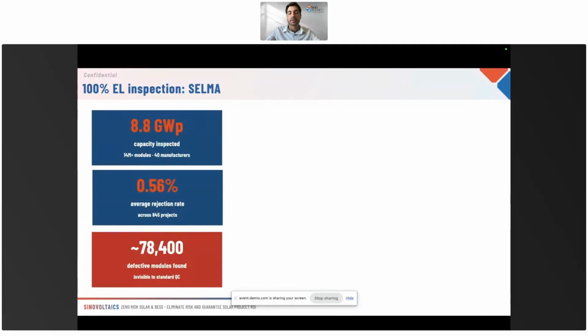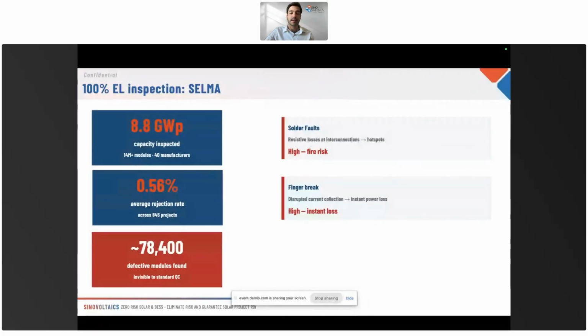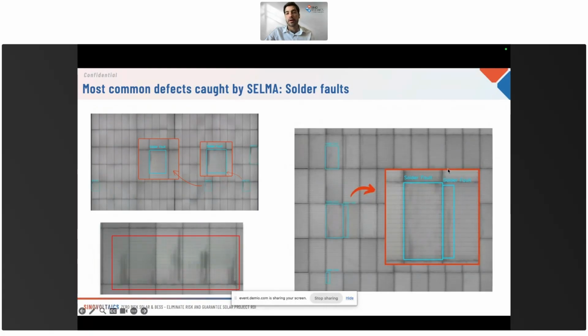We also flag here the most common types of defects this algorithm has shown. First, solder faults, which are important to detect early because they can induce resistive losses in the interconnection that can grow into hotspots, which could mean a hazard or fire risk. We also have finger breaks that directly translate into instant power loss. And finally, we have many different types of micro cracks that can propagate when handling these modules. Here are also some EL pictures showing how our algorithm detects these faults and how they look in a typical electroluminescence image. These, for example, are how solder faults look in the field.